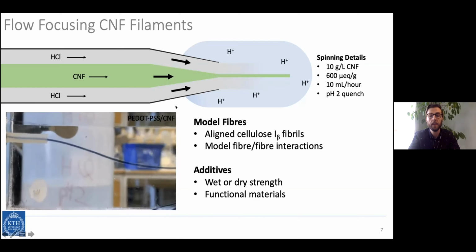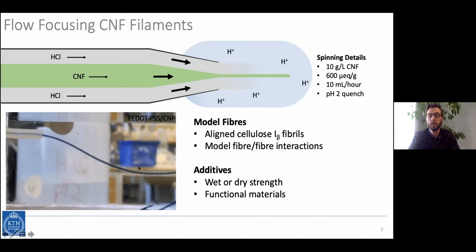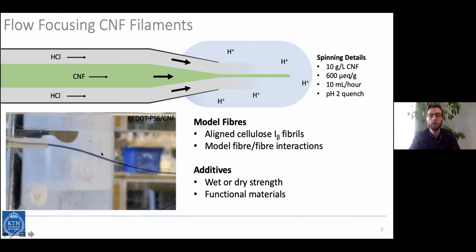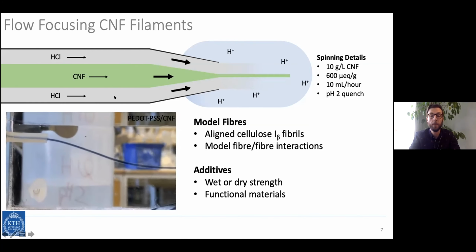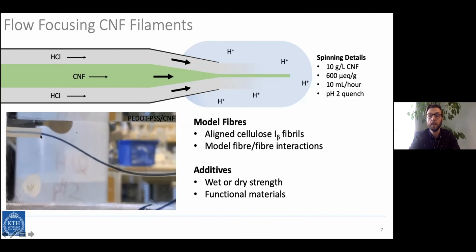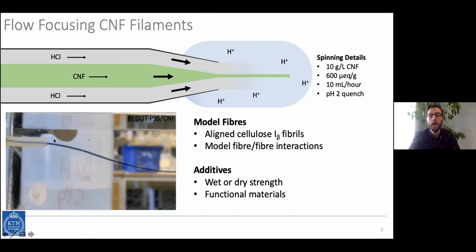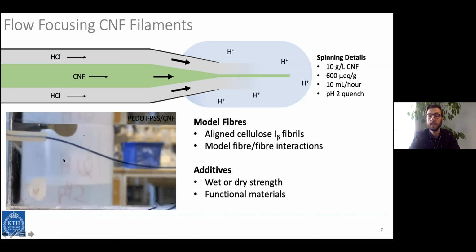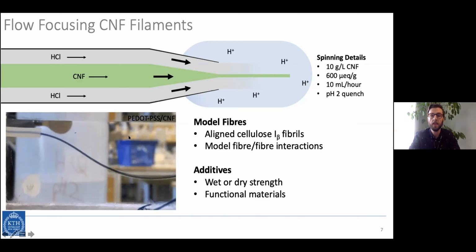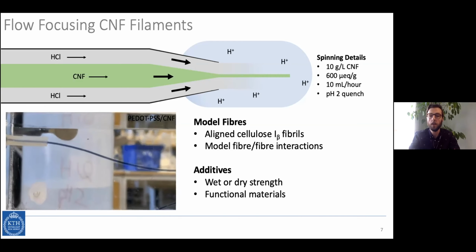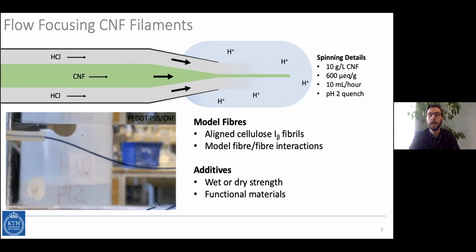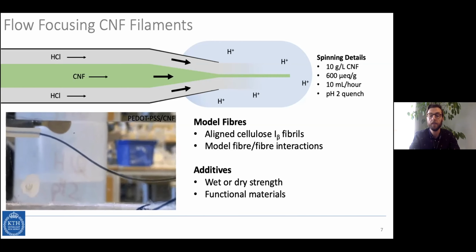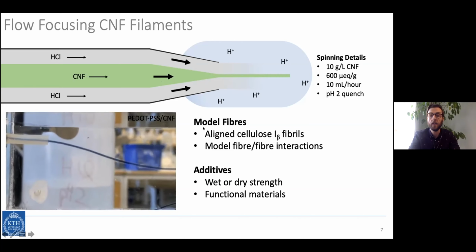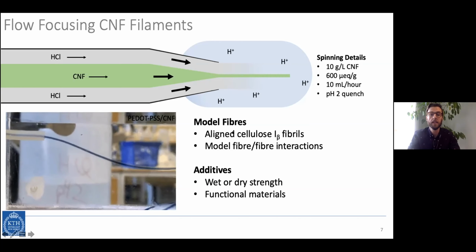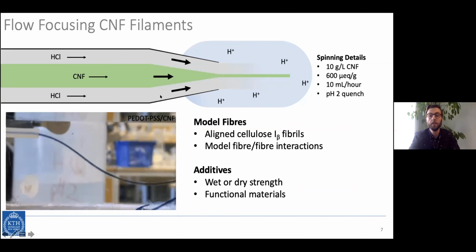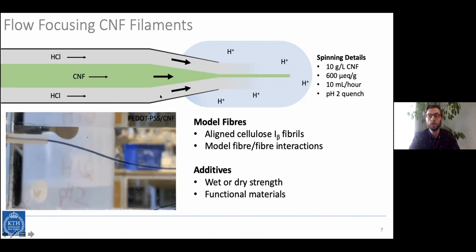So down here in the bottom left, we can see a video of an extrusion process. We have a variety of different extruders available, either 2-barrel or 3-barrel, and we can add different types of functionalities within the system. The example shown here has a dye in the system so that you can see the fiber extrusion. The great thing about these fibers is that I believe they model fibers more effectively than a classical dissolved cellulose. The CNFs are made of aligned cellulose I-beta fibrils, so this is a better model compared to a dissolved cellulose structure, which doesn't have the same crystal structure.